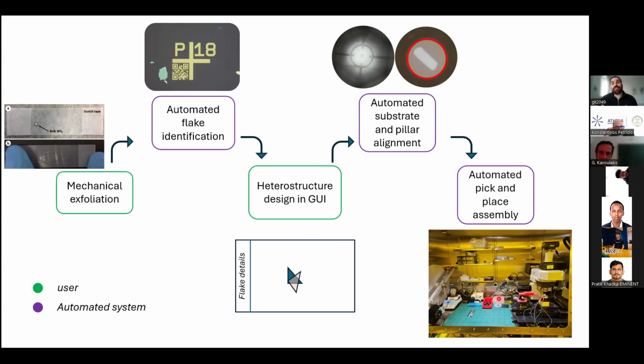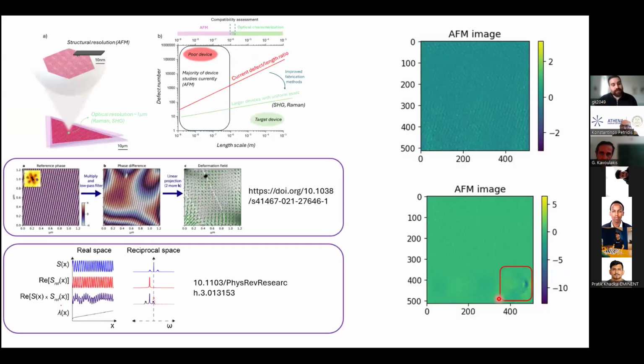And we included everything in this custom motorized setup inside the glove box, because everything needs to happen remotely. We did that because we want to avoid any extrinsic disorder in the moiré heterostructures. We don't want to have any adsorbents on the materials. We want to get rid of that, and the reason why is this one here. Our plan is to explore the homogeneity of moiré materials and their potential application in devices, from nanoscale using AFM techniques like PFM, LFM, to micro scale and then macro scale, using techniques like Raman and second harmonic generation.